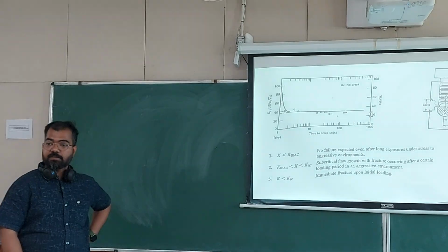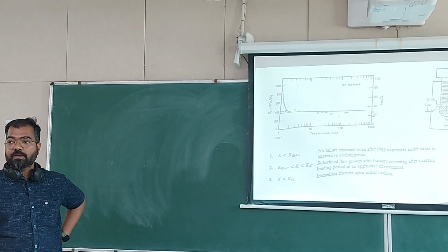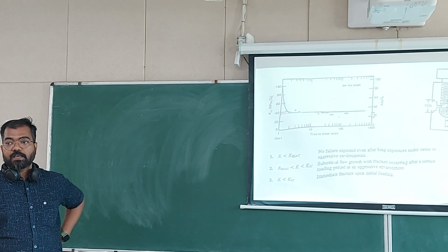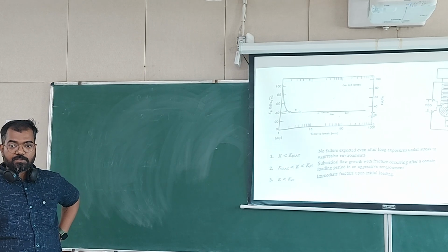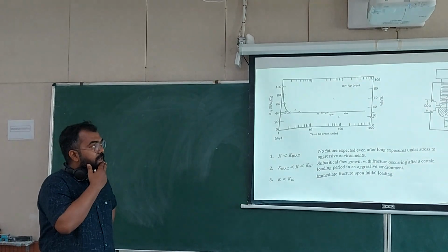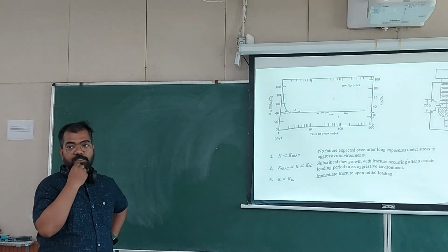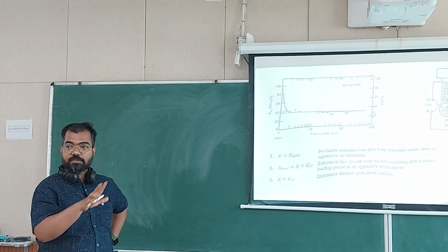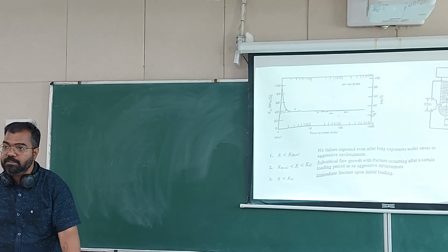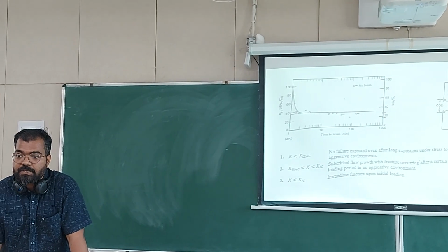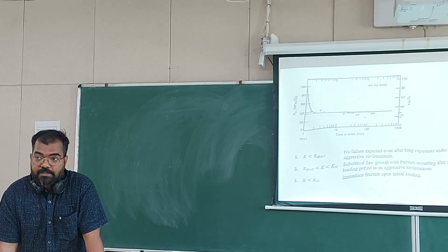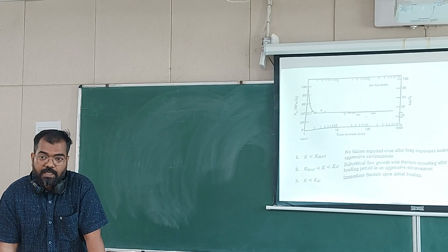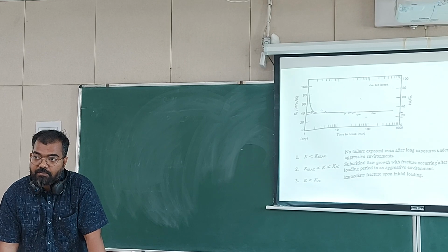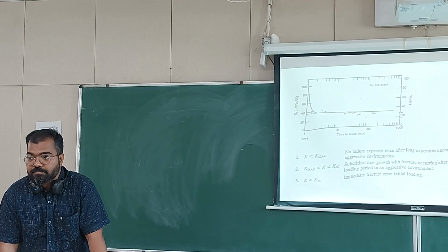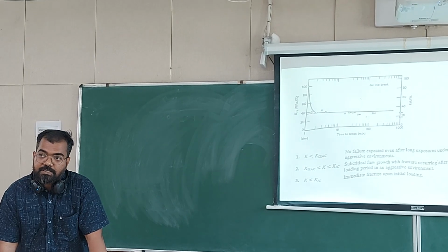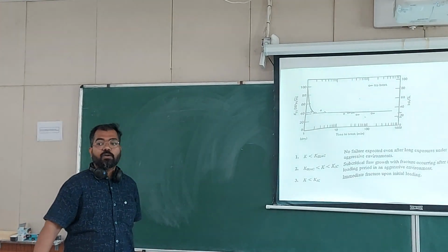With one specimen of this kind, you can find out the threshold value of K1C, which is K1 EAC or K1 SCC, stress corrosion cracking or environmental assisted cracking. Environmental assisted cracking is a vague term because environment can also include temperature. But we are not talking about that because it is a separate field, and we know what happens when you change the temperature. Because there are chemical reactions involved in corrosion, you will have the effect of free energy and Le Chatelier's principle. So changing temperature or pressure will change the reaction rate, and that will change the rate of crack growth.